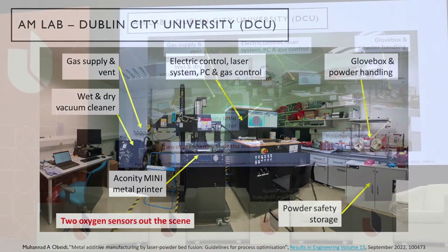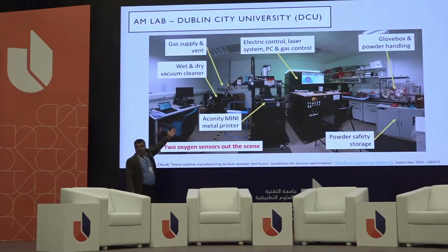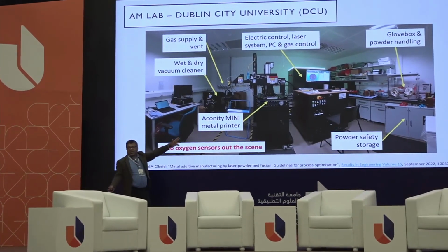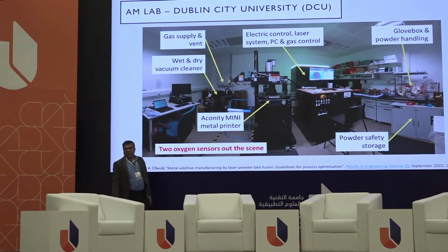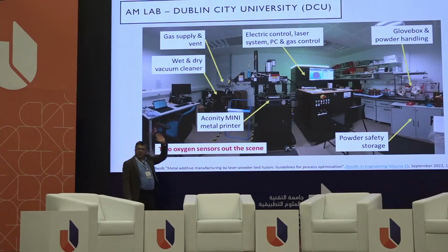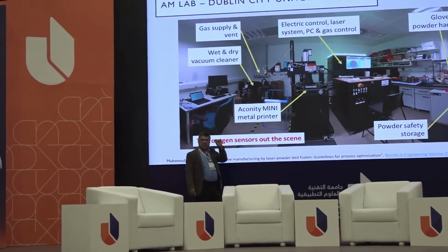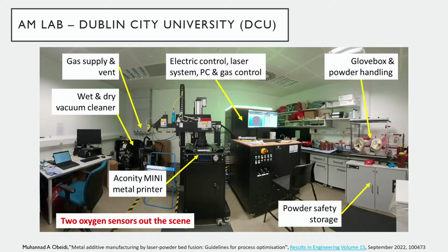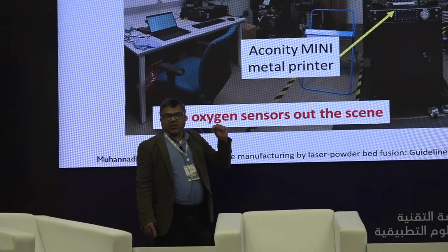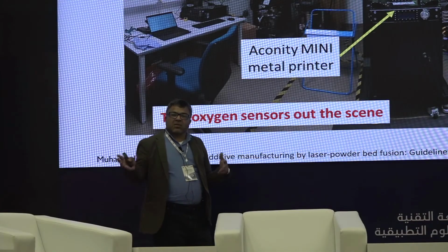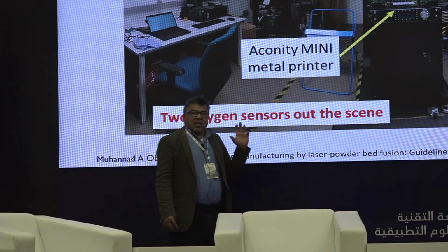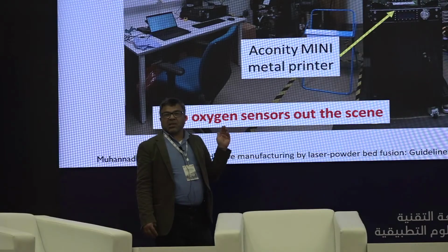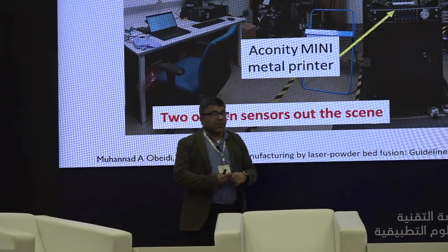We start the process by designing our part on our own laptop or personal computer using any CAD software such as SolidWorks, Creo, Fusion 360, and then save it in the format that the printer can understand and read. On the printer, we slice this part into slices by defined layer thickness. Usually here, as opposed to FDM or WAAM, wire arc additive manufacturing, the layer thickness is in micro scales. So start, for example, from 10 microns and can go maybe up to 200 microns, depending on the powder particle size, depending on the laser power. You can control the layer thickness.